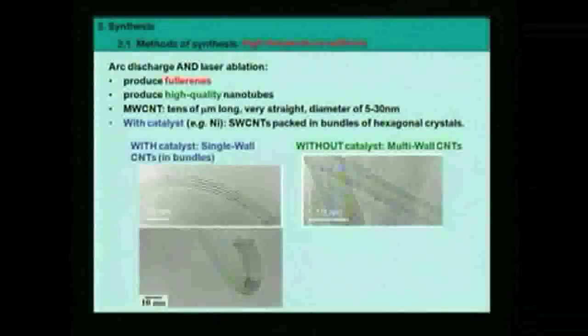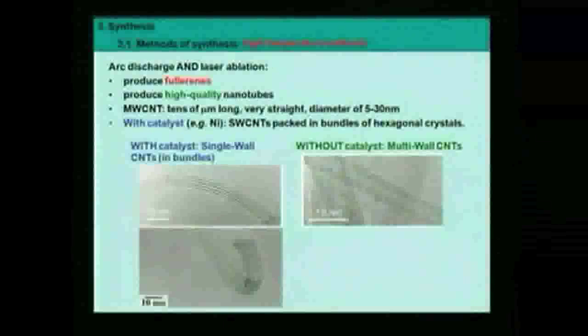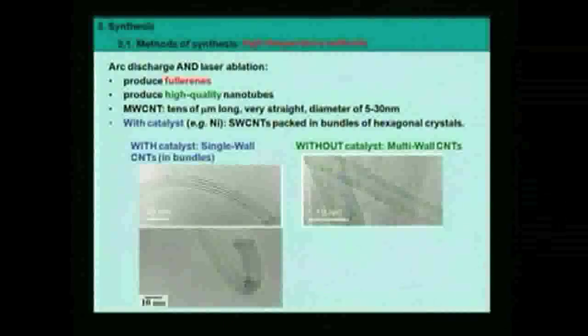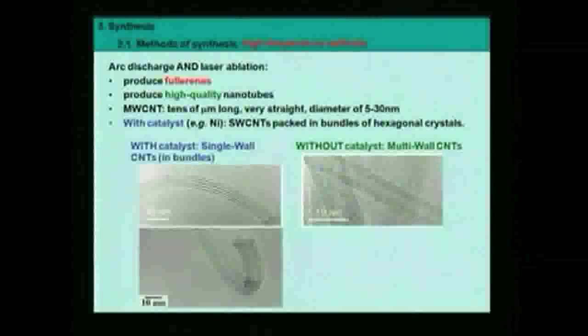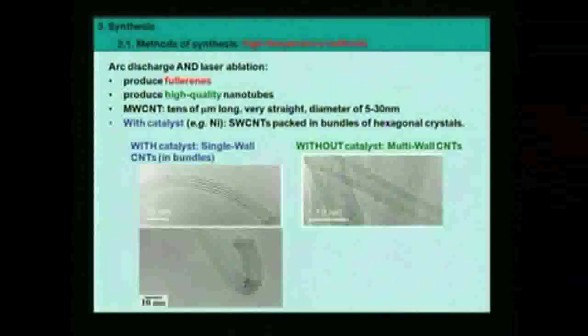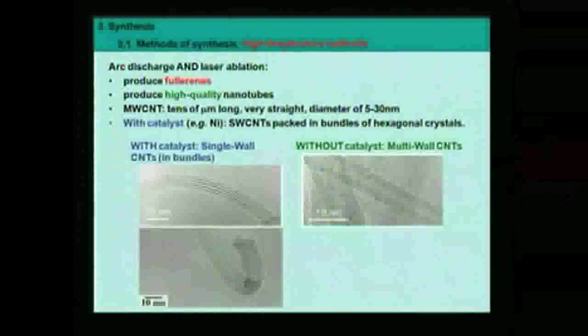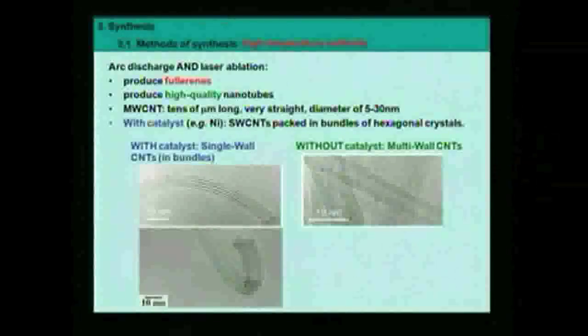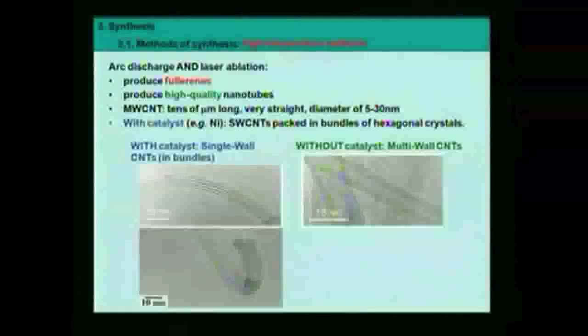Okay, so for instance, if you use platinum as a catalyst, you will have much larger diameter nanotubes. There were models to explain that due to the difference of eutectic point, but this also is not well understood yet. You will see that later when we talk about understanding the growth mechanism. We'll talk a lot about CCVD, because this technique rapidly became the most used one, and those two high temperature techniques were kind of abandoned. For this reason, there are still many question marks about the growth mechanism of those structures using high temperature methods.